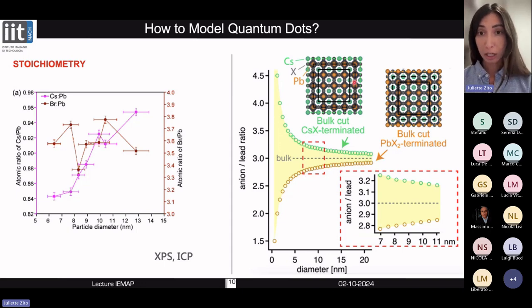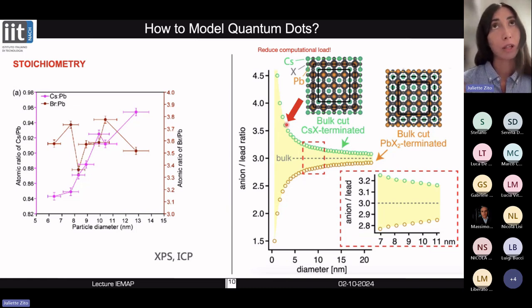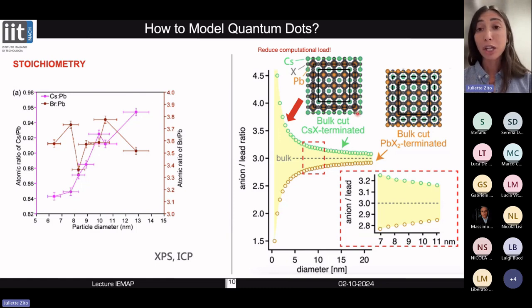So to select the correct model, we will look at the typical experimental diameter, and by comparing with experimental analysis such as ICP or XPS analysis, we will select the model with a high anion to lead ratio, that is, this cesium halide terminated model. However, in our simulations for the size, we will select a lower size with respect to the experiments to reduce the computational load, because we will then use first principle methodologies that are computationally demanding. However, we have a nanocrystal model with the correct shape and surface termination.